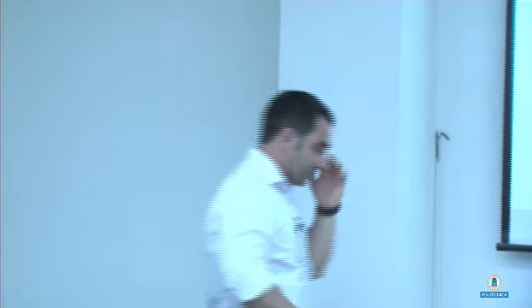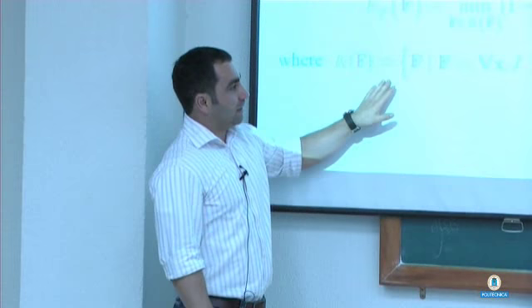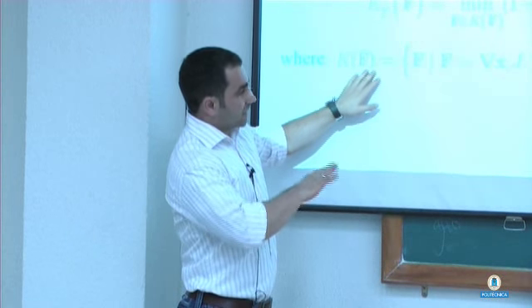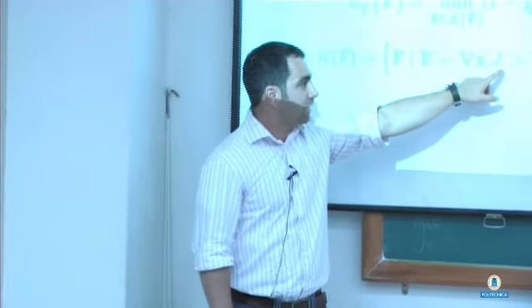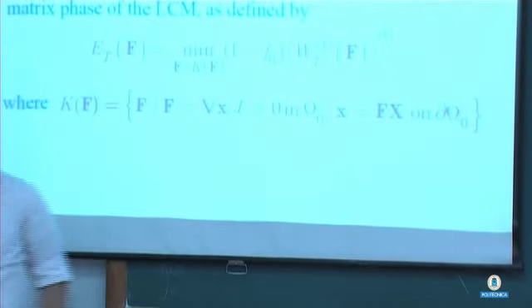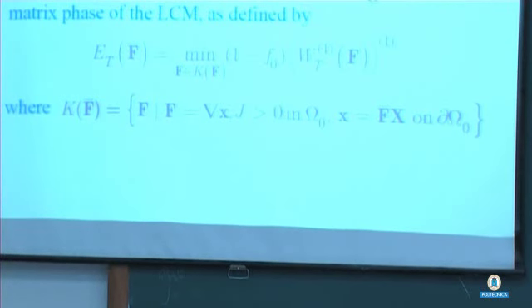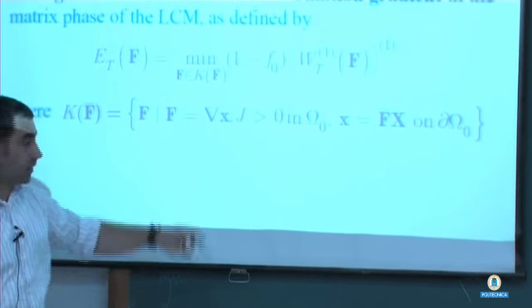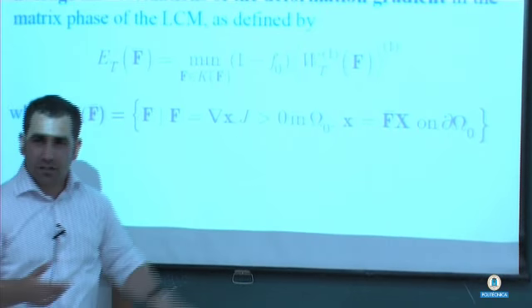A couple of things here. In reality, this is not linear. Why is it not linear? Even though this is quadratic, it's not linear because in the kinematical set of admissible fields, you have a constraint that is the determinant of F greater than 0, right? That has to do with material impenetrability. And this is a nonlinear constraint. The determinant of the deformation gradient, right, is a nonlinear function. So this is a nonlinear problem. So even though everything is linear except this, okay, forget it. It's not linear. So that's difficult to handle.